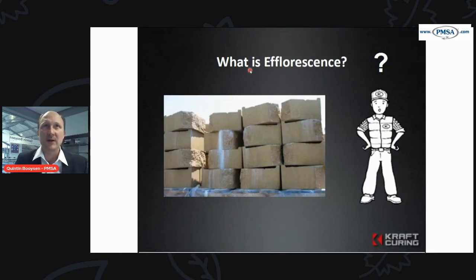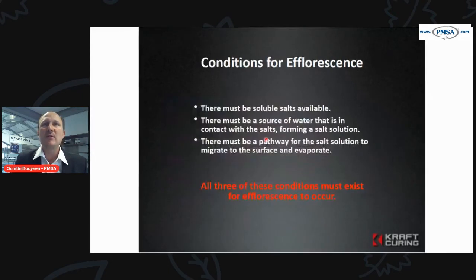So what is efflorescence? It's really the migration of those salts to the surface of the concrete, and then it's met with carbon dioxide, and you end up with a product which we would call efflorescence, a calcium carbonate. And it can be unsightly, although it doesn't normally change the strength of the concrete, but it is unsightly. And people looking at it on concrete roof tiles, especially where you start having white patching, or on paving, it's often not looked upon in a positive light.